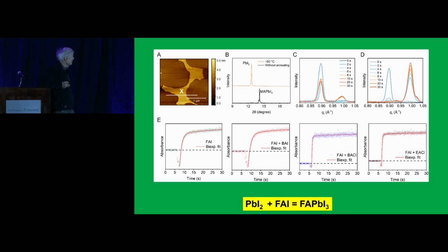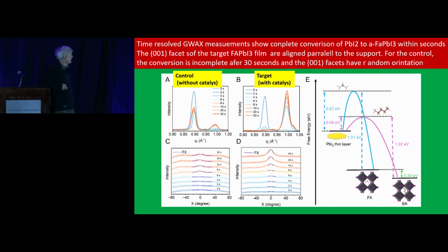And now you see how fast the reaction goes. On the bottom, you see the absorption curves. They reflect the kinetics of forming the desired formamidinium lead iodide. You see, within a second, this reaction is over at room temperature. And you get the phase pure material. That's the miracle of nanotechnology. You go from those nanosheets, you add a catalyst, in this case the butylammonium chloride, and the reaction is driven at a phenomenal speed so that you instantaneously form the black phase, which then is stable. And you can see the conversion can be monitored optically, but also by doing time-resolved GIWAXS studies. And you see that this new phase shows up within seconds.